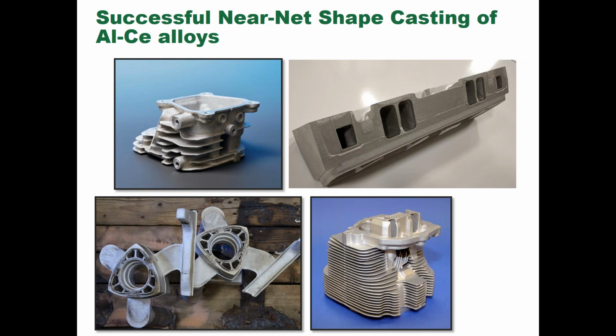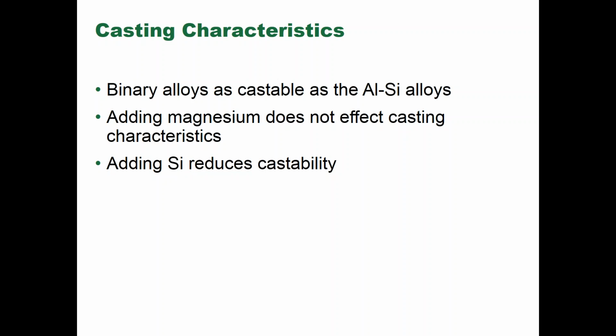That right-hand image was the cover image in, I believe, the July issue of Journal of Materials, where some of the initial work on this alloy was published. So from a casting characteristics standpoint, we can say that the binary alloys are as castable as the aluminum silicon alloys. If I'm doing an aluminum 8% cerium alloy, it has the same castability as an aluminum 8% silicon alloy. And that includes characteristics such as die filling capability, hot tearing resistance, as well as the ability to feed the casting easily.